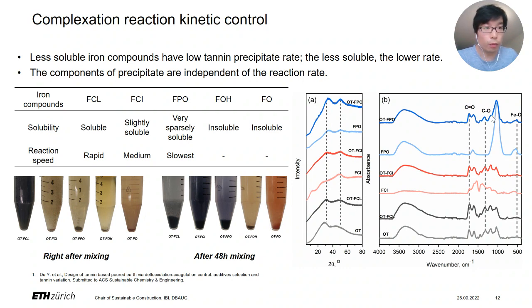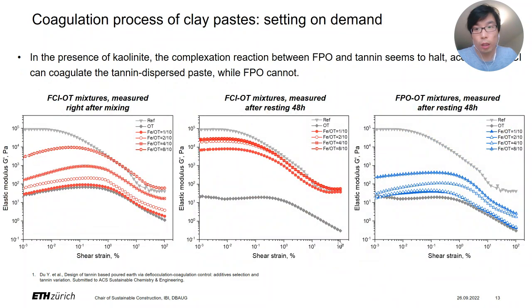But the phosphate one is a little bit different. We still have some undissolved or unreacted phosphate in the precipitate. So that means 2 days are not enough for the phosphate one to fully precipitate the tannin out of the solution. We also did some rheological experiments. We need to test whether this selected iron component can finally rigidify or coagulate our paste.